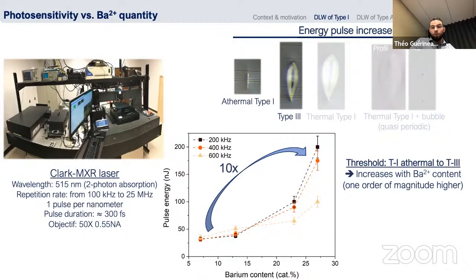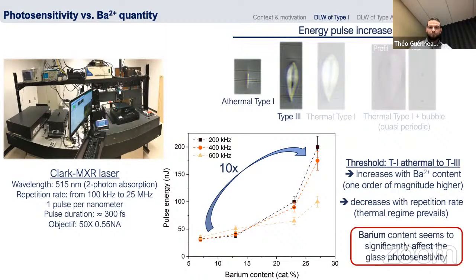But when we increase the repetition rate, we observe a decrease of this threshold, but it's kind of obvious in this case because when we increase the repetition rate, we go more and more to the thermal regime, and so this type of regime will prevail. So this is just to introduce quickly that just by changing the barium concentration, we can significantly affect the glass photosensitivity.